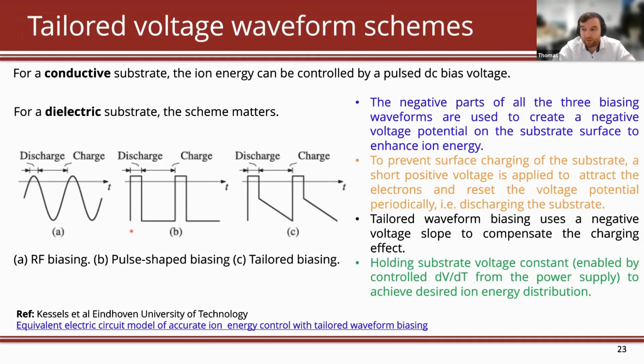So again, this is a sinusoidal waveform, positive, negative voltages. So you have a large constant negative voltage, which will obviously give you constant ion energies, okay? And then you have to quickly do a discharge part of the cycle. So you have to go positive to remove any electron. With a metal electrode, that's not too important, but you do want to go slightly positive and then mostly stay negative in order to tailor your energies, okay? So the energy you get is going to be the plasma potential plus this voltage here, okay? So basically by monitoring the voltage of these tailored waveforms, you're directly monitoring your ion energy, okay?